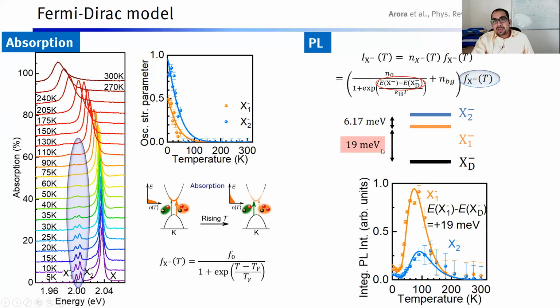So if we fit these spectra now with this function, with this number, then we find that this number turns out to be 19 meV. And these spectra fit very beautifully actually. In fact, this small fall in the beginning is also reproduced and then it rises and this falls. So this is just a single parameter fit essentially. And we find that the dark trion state in tungsten disulfide should be 19 meV below the bright trion state, the lowest bright trion state.